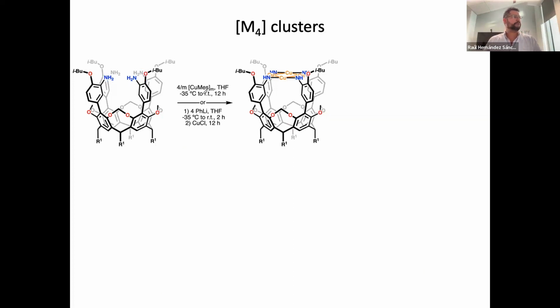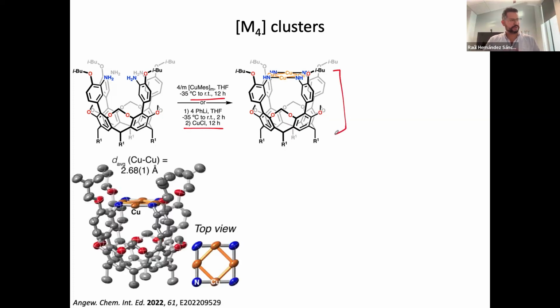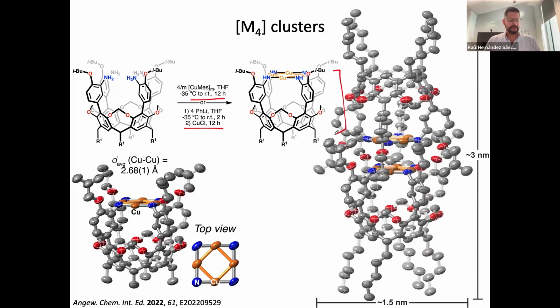And so by doing that, we were able to synthesize clusters under different conditions, as shown there, to make this type of copper cluster. These copper clusters we reported about 2 years ago. The copper to copper distances are fairly short, on the order of 2.7 angstroms. They actually form a dimer in the solid state, as shown there.